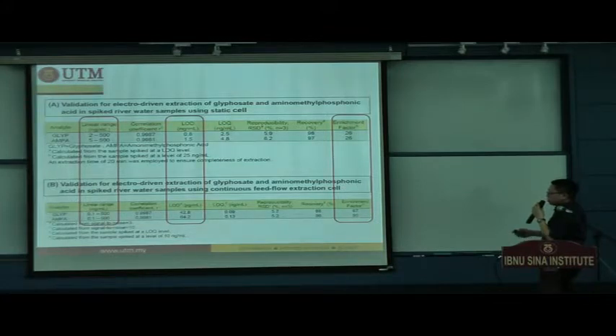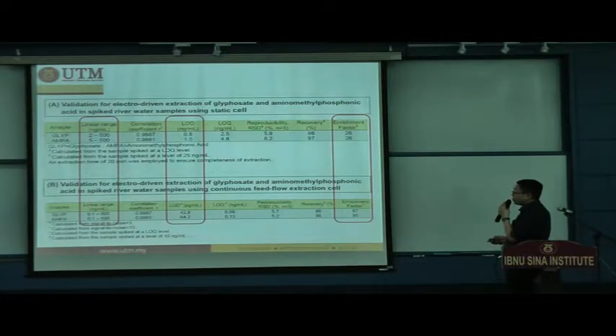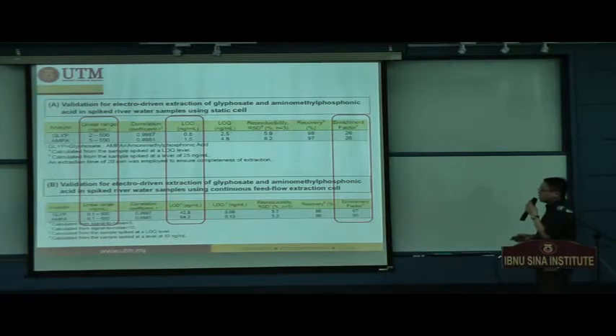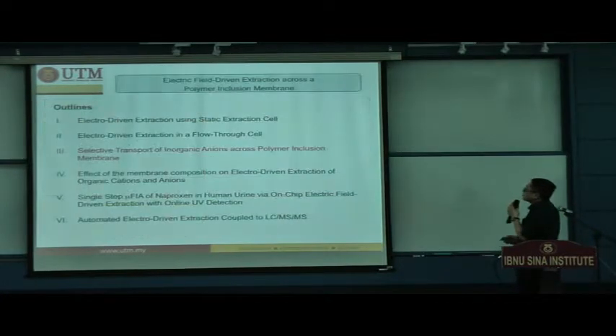But we also tried to flow 20 milliliter samples, which can increase the enrichment factor up to 200. But it will double your extraction time. So it also depends on what kind of LOD you are looking for. If you are looking for a LOD which is lower than this, you can increase the sample from 10 to 15 or 20 milliliters in order to get a lower limit of detection.